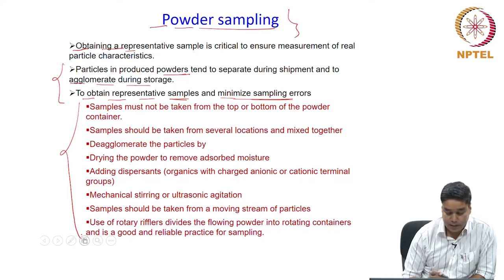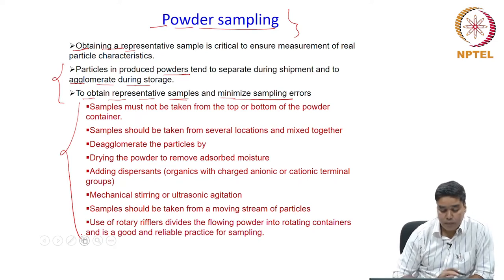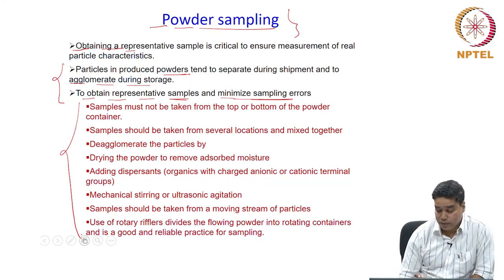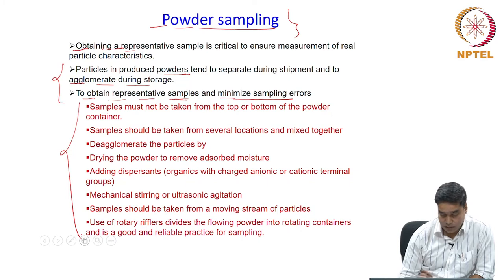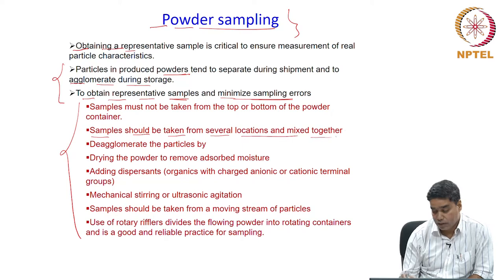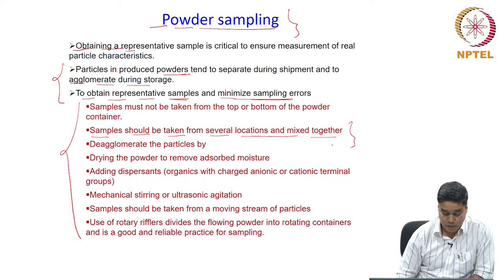Good practices to follow when collecting a representative sample: first, samples must not be taken from the top or bottom of the powder container. Samples should be taken from several locations and mixed together, which will ensure a random mix that is a good representative of the entire lot of powder.